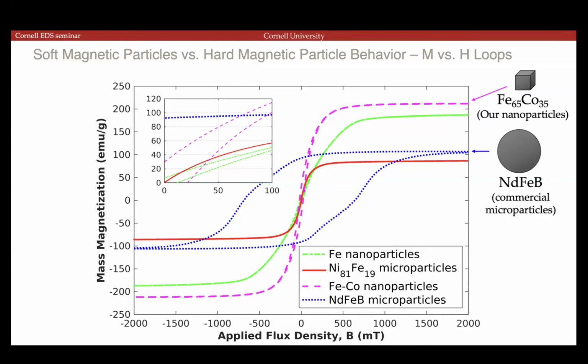So in our case, we could also still achieve this if you have a single domain, but as soon as you have a large area material, then what contributes to the width here is a lot of times the domain walls. So if this material, the neodymium iron boron, we simply draw as multi-domains, then as you're trying to magnetize it, when the magnetic field is applied, this domain wall has to shift so that more of the material is magnetized. But there are pinning sites that resist the shifting, resist the magnetization, and force it to wait until a larger field is applied and then magnetize it.